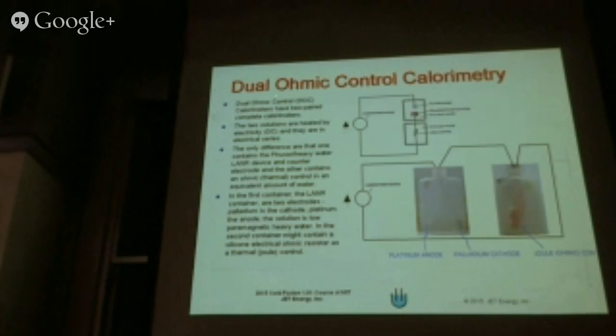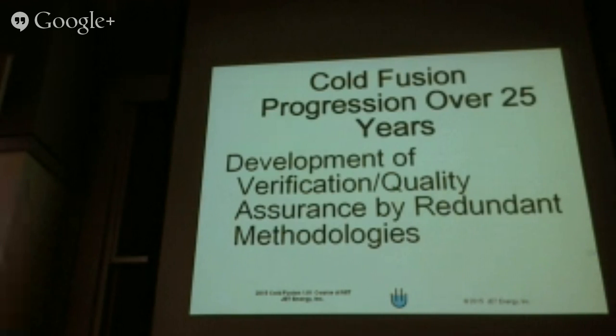Here, for example, is a dual ohmic control. This is what we showed at the open demo in Peter's office in 2003. Here we can see the palladium cathode. Here's the platinum anode. This is unfilled, so we fill them both with water. And here's the ohmic control. We put them in electrical series with a current source. It's a very easy, simple experiment, well characterized. And we were able to show with less power, with less voltage across there for the same current, we had a higher temperature. And we were able, in his lab, for 5 days to show an energy gain of 4. And we'll show you some of that data.